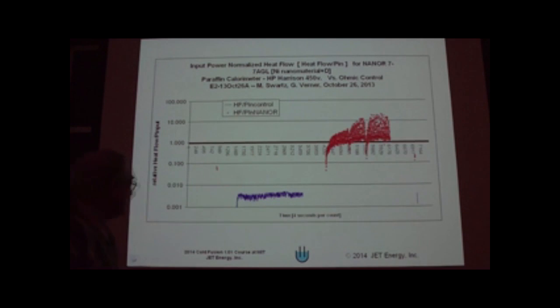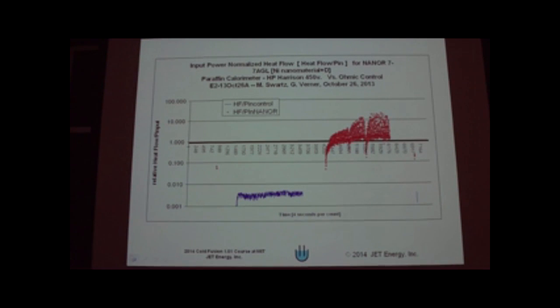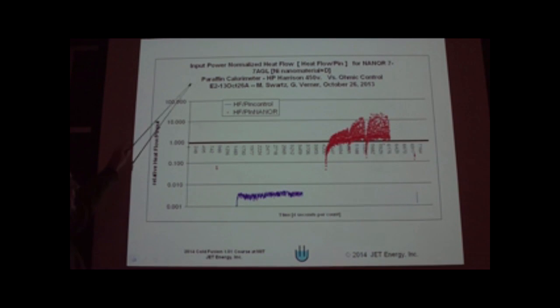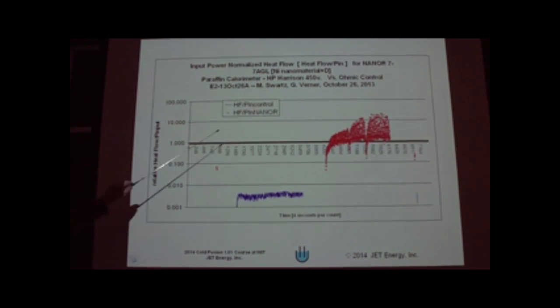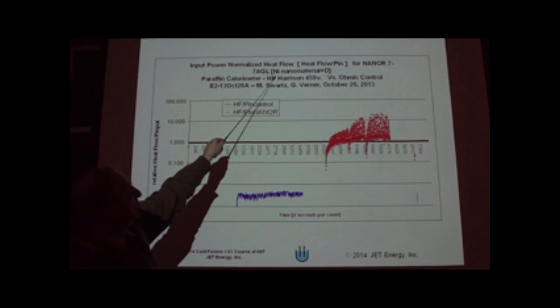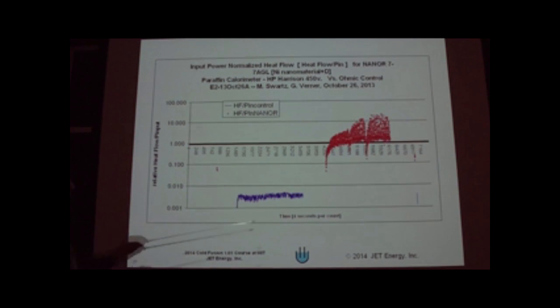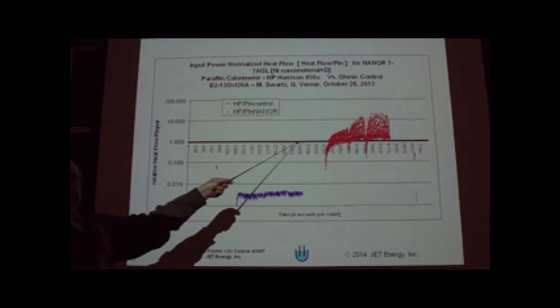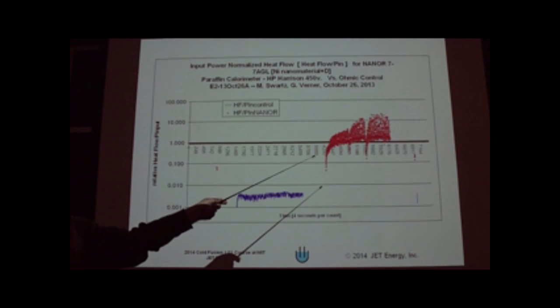Nickel nanomaterial. No clapping till we get these out. Commercialization, we've got a long way to go. Here again, the input power normalized. This also is with only nickel with the D, and again we take the ratios. By the way, this is not with the delta T. This is the corroboratory measurement where we look at heat flow.